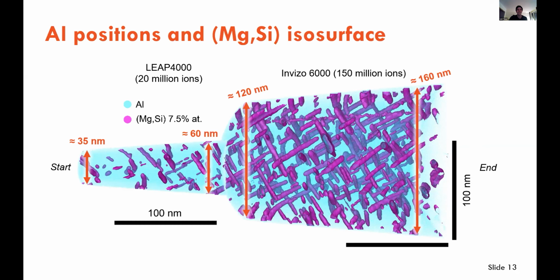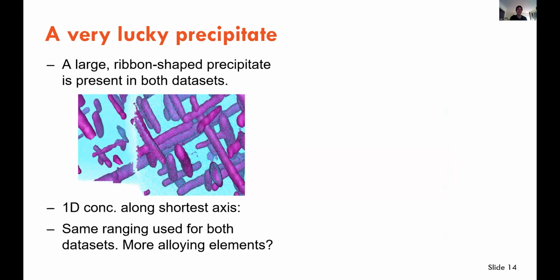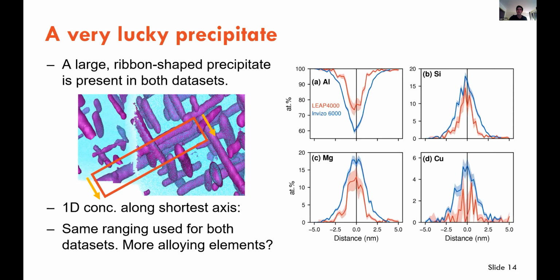Very, very cool. So as I was hoping, there was actually one very lucky precipitate, which is present in both data sets. So you can see it there, which is exciting because it allows us to not only do chemistry over all of the precipitates, say on a proxigram of the iso surface, you can see there, but actually along an individual precipitate. And quite surprisingly, in this particular precipitate, there was actually a difference in chemistry. So in the LEAP 4000, it was a little bit poorer in the alloying elements, silicon and magnesium.